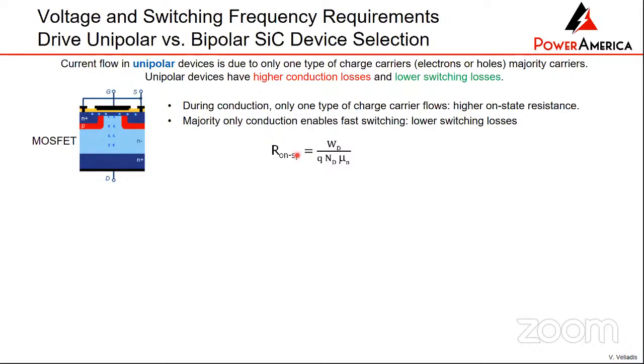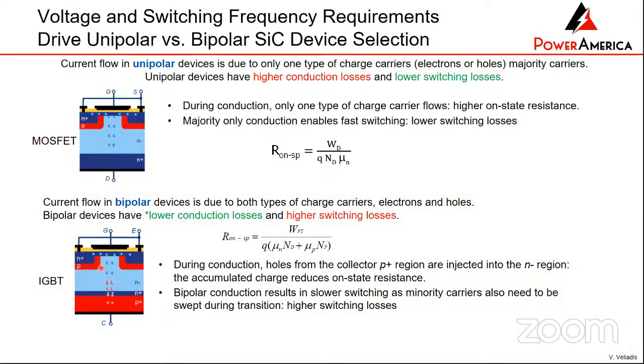Now, a second type of consideration is a bipolar device. If you look at a bipolar device, you've got both electrons and holes going through the device. So now your resistance is a lot lower because the conduction has both the electron contribution and the hole contribution. However, the fact that you now have both electrons and holes means that when you switch the device on and off, it's going to be slower because you've got two types of carriers that you need to sweep out. And the fact that it's slower means you've got higher losses.